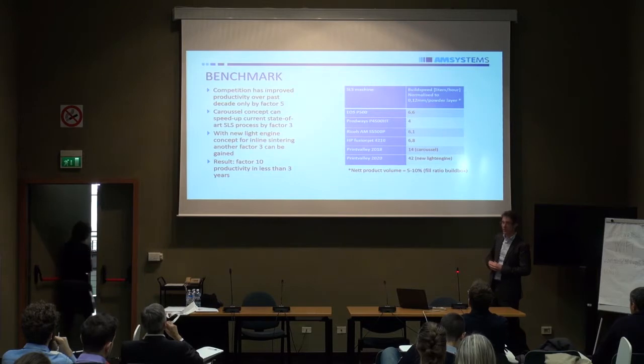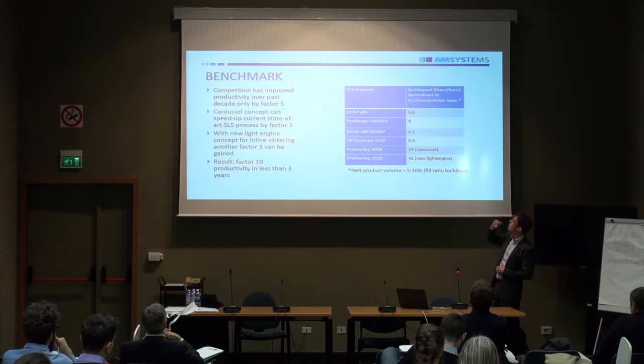To do some benchmarking, how do you compare these different systems? We do that with how many liters per hour of product you can produce. For example, this new system, the EOS P500, they have in the brochure that they can produce 6.6 liters per hour. And if you look at the Print Valley, then with the same process you can make almost a factor of 3. So then you can make a big step in this throughput.